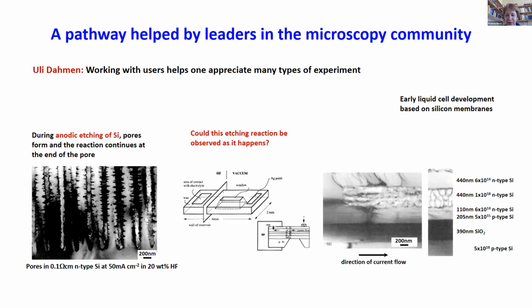So at the time we had our own research programs, and these images are from an early liquid cell development project where we were trying to get anodic etching of silicon using HF electrolyte through a layer of conductive silicon that was embedded between two intrinsic layers. So an interesting project that actually completely failed, I would say, but was still fun to try out.